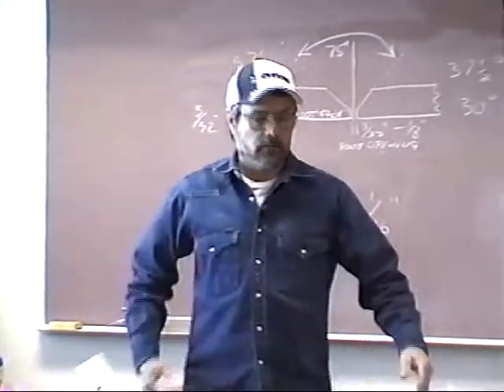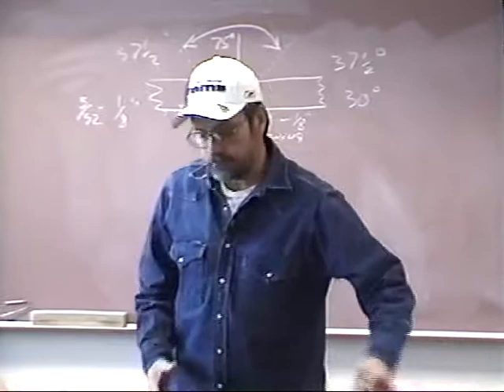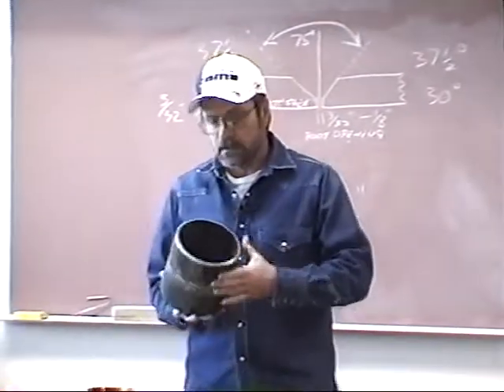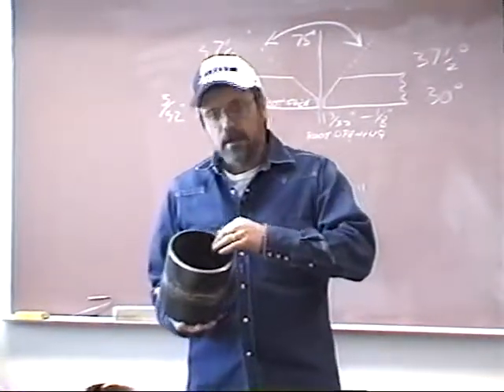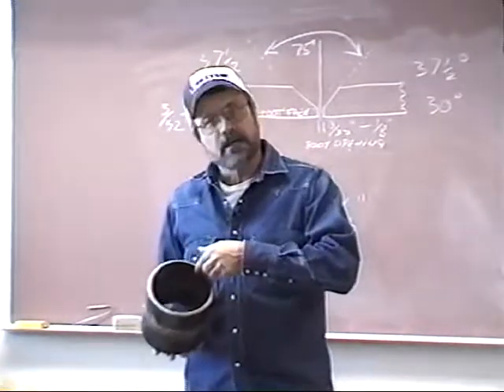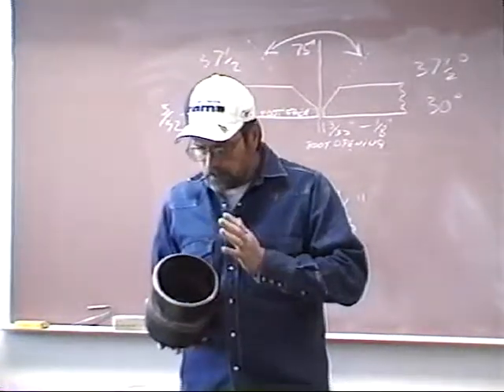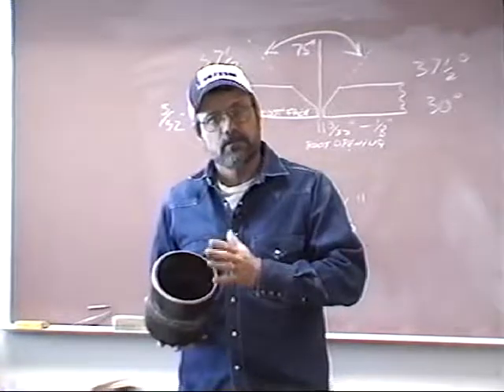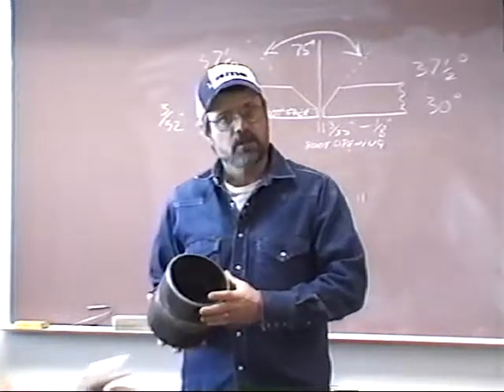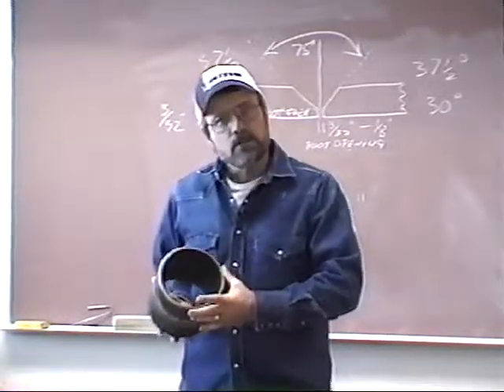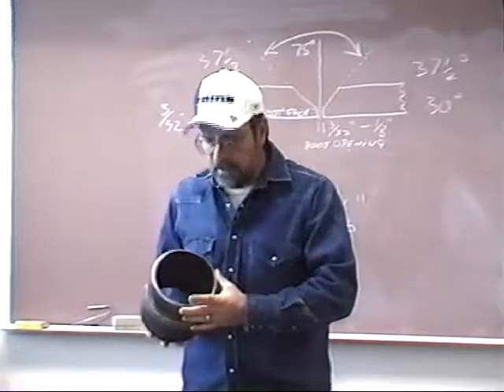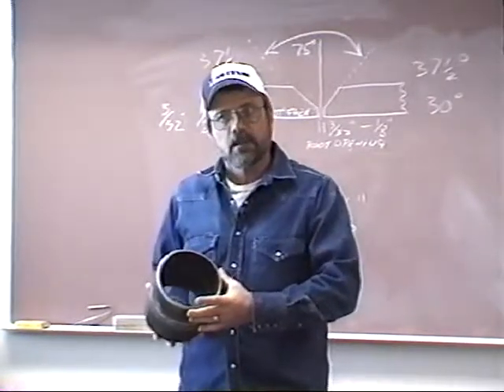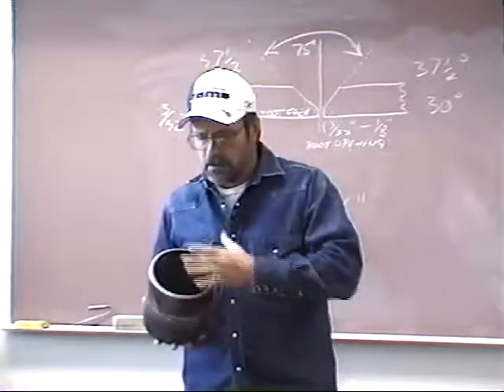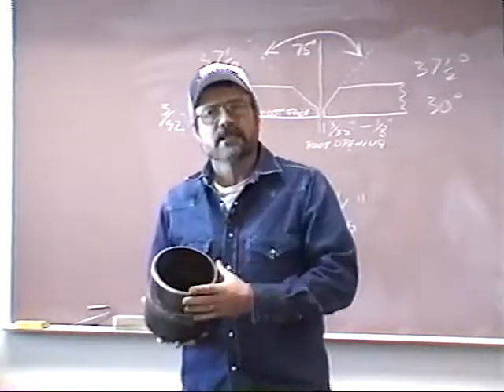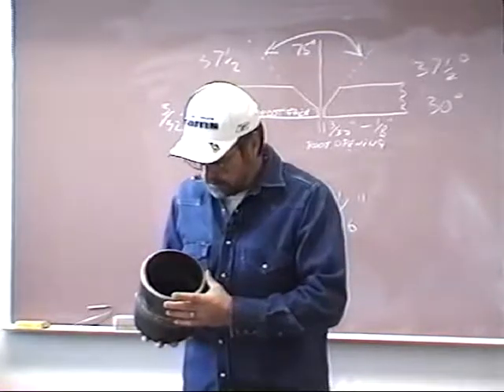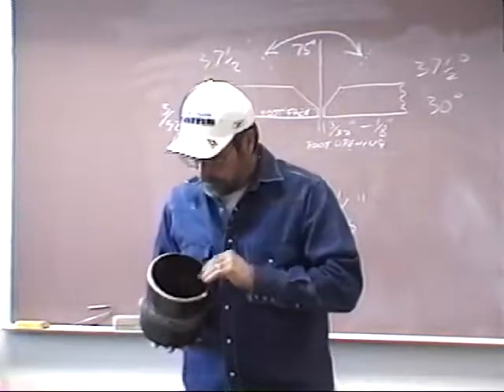Now individually, I'm sure Jeff and I have worked with each of you about how to get these things lined up. Most codes will allow you 1/16 of an inch of misalignment on the inside. And not all pipe is going to be circular. It may be a little egg-shaped at times. So you want to get as accurate a fit up as you possibly can. And if you do have a little egg-shaped pipe, try to split the difference a little bit so that you don't exceed 1/16 of an inch of mismatch on the ID, the inside diameter of that pipe.